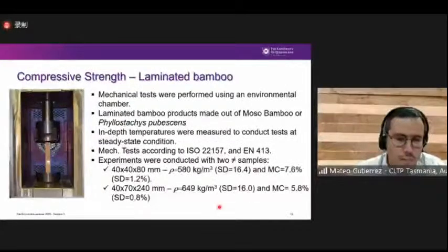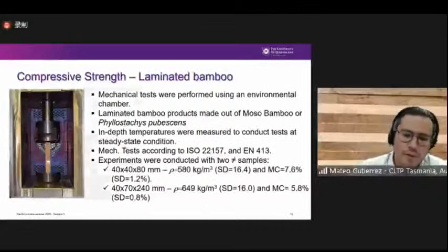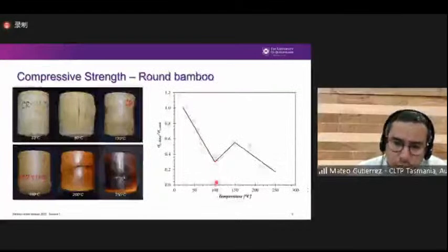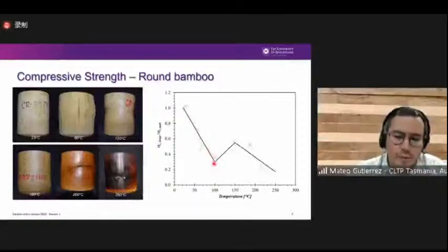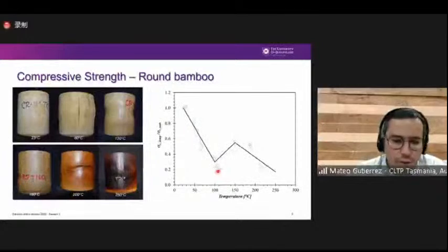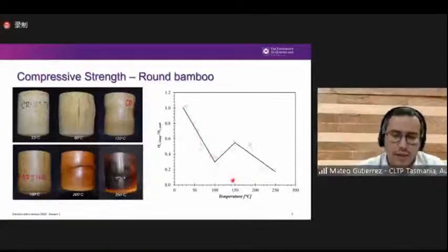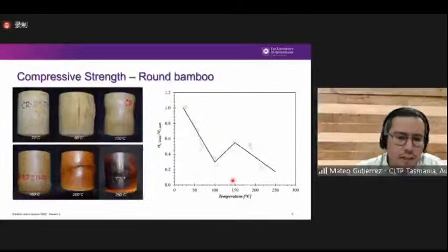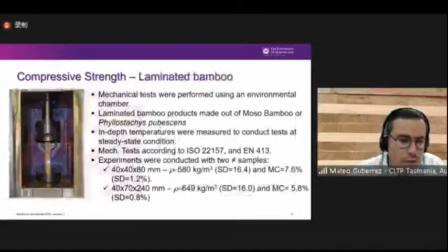After testing these raw bamboo samples, as you can see from the previous graph, at 100 degrees we almost lost 70% of the strength of bamboo. And that really raised some concern because 100 degrees is a very low temperature in a fire condition. So we thought that it was worth testing laminated products because they had the capacity to resist longer fires, and that can create also some charring that will protect the inner part of the material. So after testing this raw bamboo, we decided that it was a good idea to test laminated bamboo products. So that's when we started focusing our research on laminated bamboo.